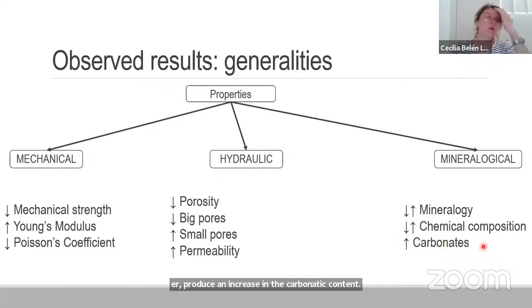On the other hand, we were also able to observe that there was a reaction between the glauconite and the CO2. What I forgot to mention was that in the grain-to-grain contact, there were clay grains. These clay grains also reacted with the CO2 and ended altering also the porosity and the distribution of the pores.